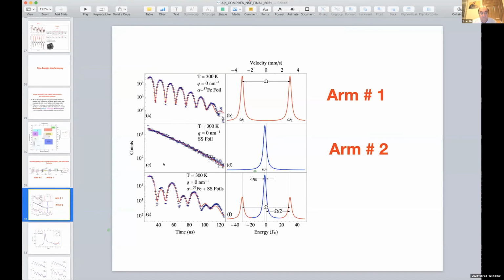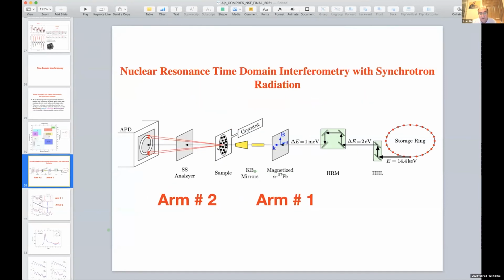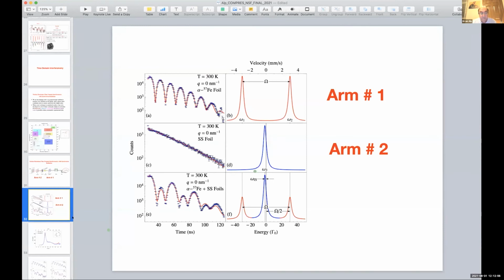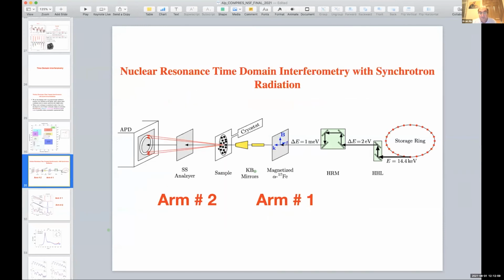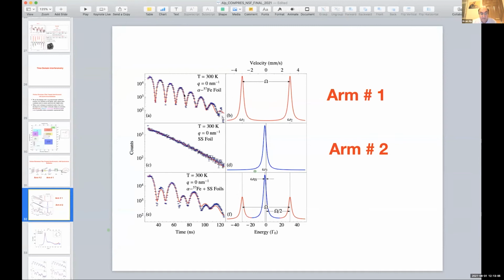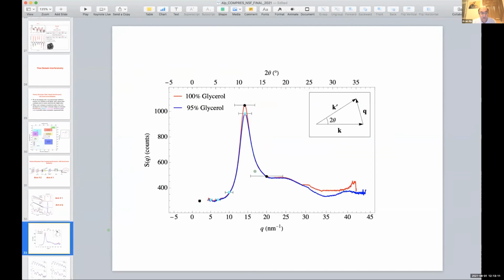So what happens is that if this sample destroys the coherence, you're going to see a pattern like this. If the sample maintains the coherence by freezing, you're going to get a pattern like this. So these two extreme cases are the beginning and end of our interferometric signal. If you take, for example, glycerol and measure S of Q, nobody has managed to get data at this very low Q and at this very high Q because the count rates are so low. So our breakthrough, the one that we developed, allows us to actually measure across all Q points.